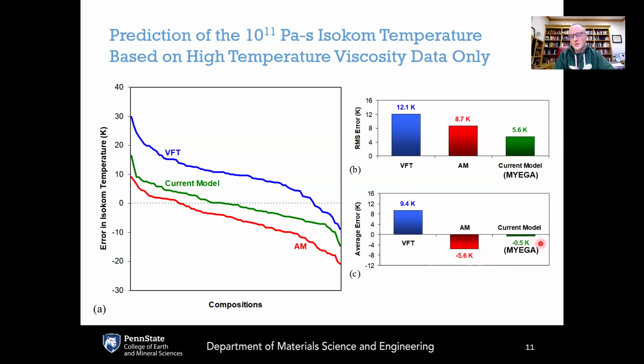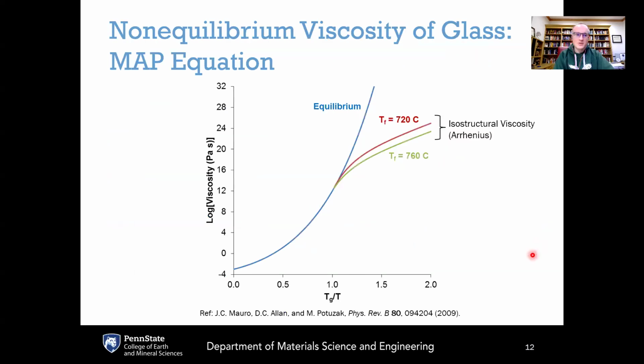With the MYEGA equation, this was able to give the most accurate prediction. Actually, the prediction was within experimental error, so only about half a degree off on average. Now, the MYEGA equation, like the VFT equation, really just gives the viscosity temperature relationship for the equilibrium liquid or metastable equilibrium supercooled liquid. And that is what's being shown here in blue.